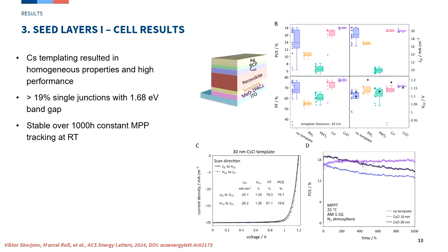We can implement that into single junction solar cells, using only the co-evaporated perovskite with a seed layer, and you see the results here. You're getting roughly 18 to 20% efficiency, which is quite good for that band gap and technology. You see the spread in efficiency compared to the standard is much reduced. That's what you want to have.